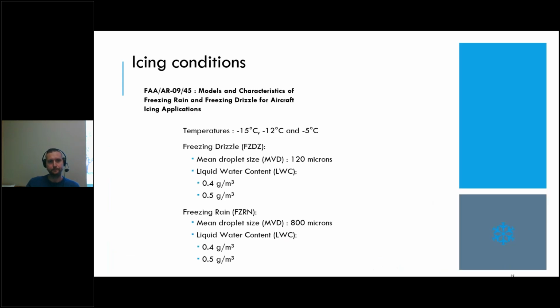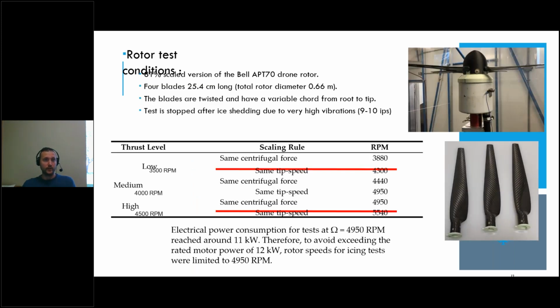Next slide, please. To define the icing conditions, we use the FAA AR0945 documents because we wanted to test both freezing rain and freezing drizzle precipitations. So for the freezing drizzle, we went with the droplet size of 120 microns, while for the freezing rain, we increased the droplet size up to 800 microns, so very large droplets for precipitation. And temperatures selected were -15, -12, and -5 Celsius degrees. Next slide, please.